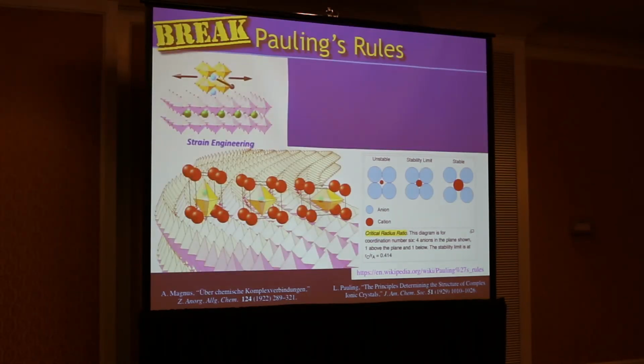When you're doing this combined substrate thin film game, it becomes possible to violate that rule and actually make it so that you can have cations rattling around inside cages. And that can be extremely useful. So having a cation that rattles around inside of a cage allows you to break inversion symmetry. So maybe you want to have a superconductor that lacks inversion symmetry. Maybe you want to have ferroelectricity, multiferroics. All sorts of examples where you would love to have cations rattling around inside of cages.